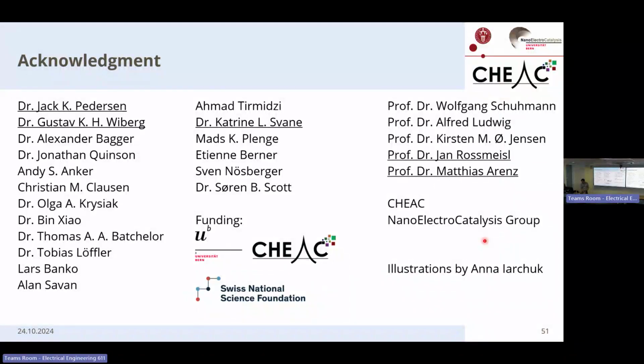I can comment on it, and unfortunately this is not my work, it's work from Alexander Bagger, and he looked into the selectivity for the CO2 reduction on copper-based alloys. And here, as I understand it now, if I look at these results, we see again that the statistics play a role. Because you now introduce a variety of different active sites, you lose control over your selectivity. You lose control over the amount of different active sites you have. So while you get an active site that is very good for one pathway, you also create other pathways.